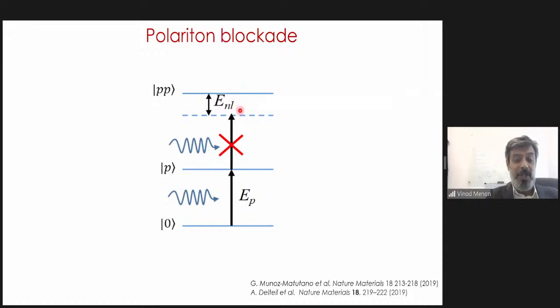And this blue shift of energy that I have here means that the second photon cannot get absorbed inside the system. So this is the idealized hypothetical scenario that I'm talking about. But if you can realize this, what you have is a single photon turnstile, where one photon comes in, it creates a polariton, the next photon comes in, it just goes through because it cannot get absorbed inside the system. And the result of this is that if you look at the photons that are coming out of the system, the photons will show some kind of correlation because they know the presence of each other, right? And there has been preliminary evidence of this in these polaritonic systems.